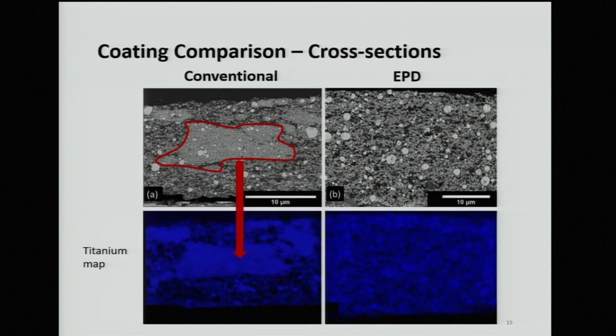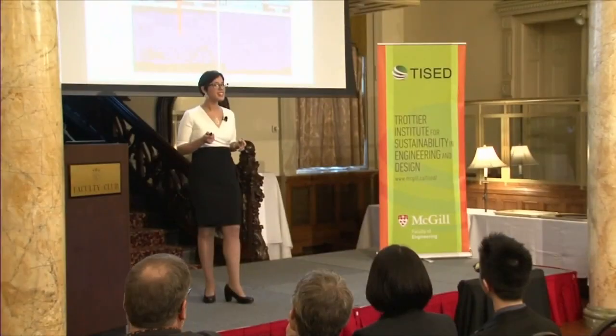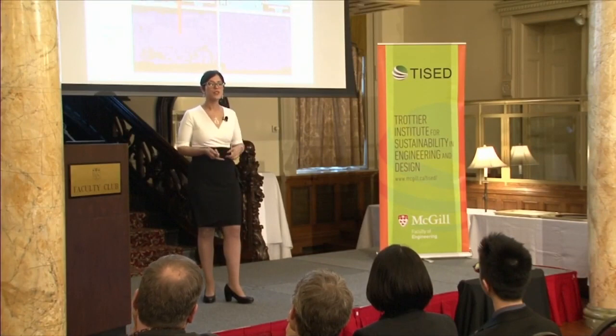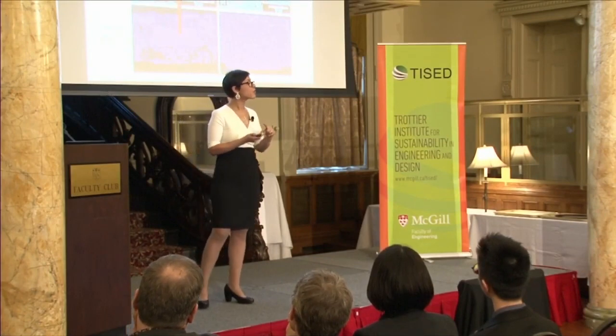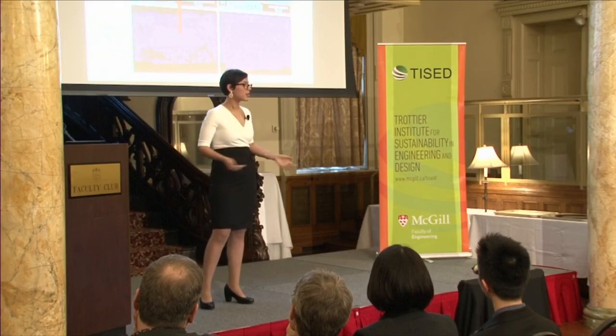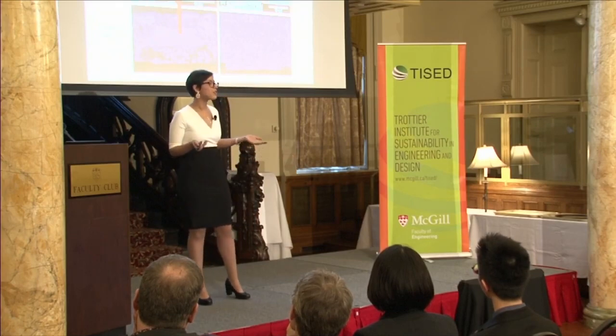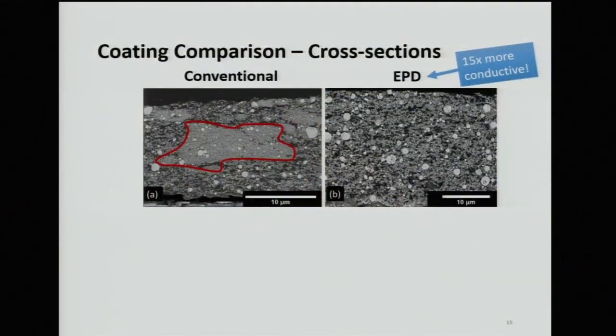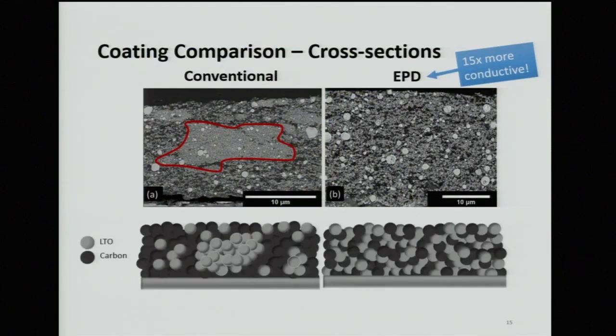With EPD, we can say we have a more uniform coating. Now, if you remember what I said earlier, the conventional fabrication technique doesn't make very uniform electrodes, and now we can visually see that. So we can say, so far, that EPD produces very uniform electrodes that perform really well at fast rate. But what is the connection between the uniformity and the rate performance? Well, we measured the conductivity of both of these electrodes, and we found that the EPD electrode was 15 times more conductive. So let's look at a schematic of these coatings.